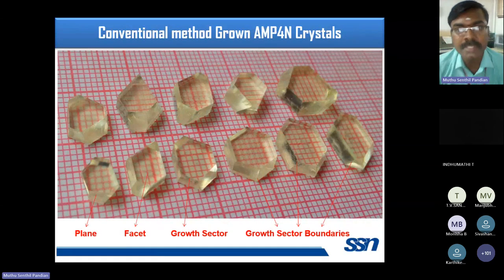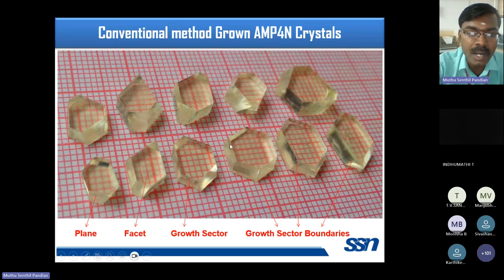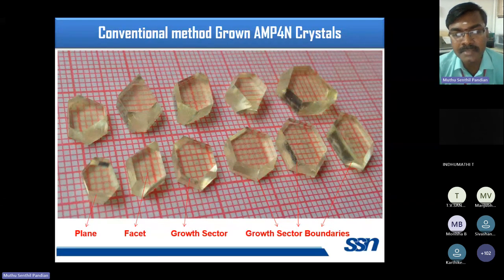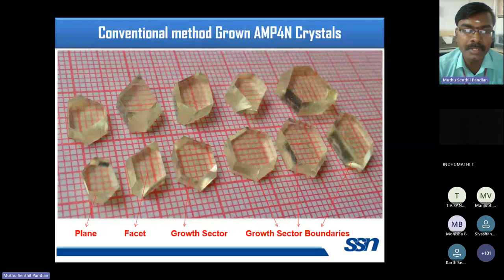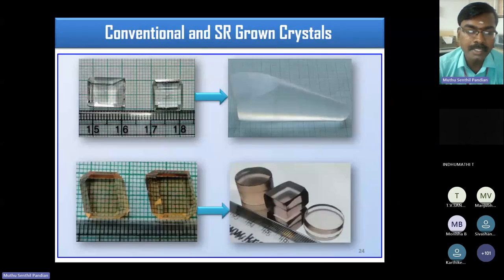So this is the conventional method grown AMP4N single crystal. If we focus on any one single crystal, all the single crystals have different planes, facets, growth sectors, and growth sector boundaries. But from the application point of view, only the phase matchable portion is useful and the other portion will be cut off after cutting the phase matching angle. For devices like frequency doublers and optical parametric amplifiers, phase matching needs to be achieved. Otherwise, the conversion efficiency would be very low. So from this point of view, this SR method has given the solution and it is possible to grow the crystal along its phase matching direction.